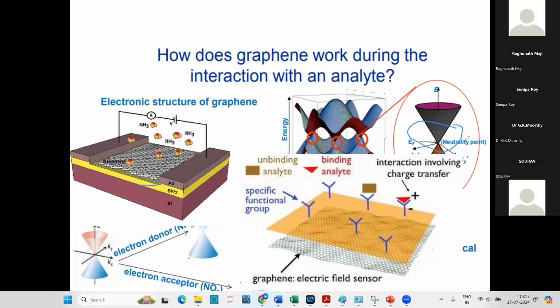That is the first and foremost criterion of a gas sensor, because you have to manipulate it when gas is coming or when gas goes off from the chamber or from the environment, when resistance is decreased and when resistance is increased. That is only possible by modulating the forbidden energy gap. In gas sensor characteristics, I have already shown you that when resistance is decreased, the forbidden energy gap is less. When resistance is increased, the forbidden energy gap will be more. In this way, you have to manipulate the forbidden energy gap. That is only possible when graphene is added with some functional nanomaterial. Here it is graphene oxide actually. So this is the case.